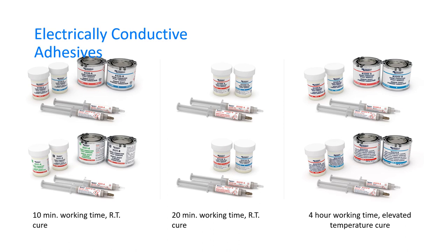Looking at the packaging, these do not come in a cartridge. They're simply too thick to dispense through. So I've sectioned them off here. On the left is the 10-minute working time. These will cure at room temperature. That's the 8330 and the 8331. In the middle, we have the 20-minute working time. These will also cure at room temperature, and that's the 8330D and the 8331D.